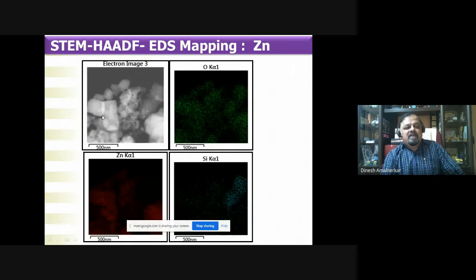You can clearly see the faceted growths here. The faceted growth here, distorted faceted growth here. And when you compare with the elemental mapping, you can see oxygen everywhere, oxygen, oxygen, oxygen, oxygen, zinc, zinc, zinc everywhere. So there's zinc oxide. But suddenly this particular patch, if you look at it, there's silicon and there is oxygen. So some kind of silicon oxide must be present here.